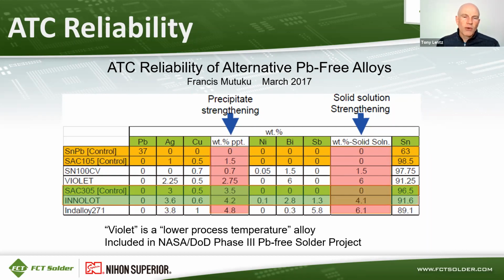So the first column with the blue arrow that's labeled precipitate strengthening shows the concentration of the elements that participate in precipitation, which means they solidify out of the matrix as individual particles or intermetallic particles like Ag3Sn. And then the right-hand column that says solid solution strengthening is the concentration of the elements that stay dissolved within the tin matrix and provide a more stable effect over a period of time. For example, SAC 105 only has 1.5% of precipitate strengthening elements and no solid solution strengthening elements. So it's going to lose strength over time.